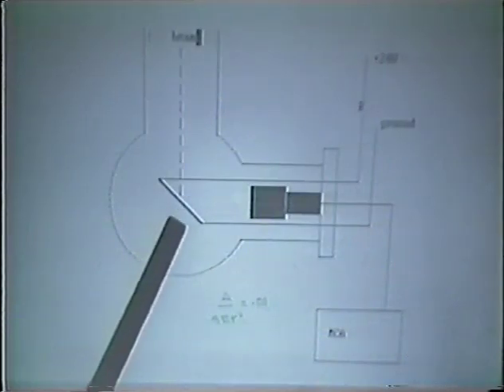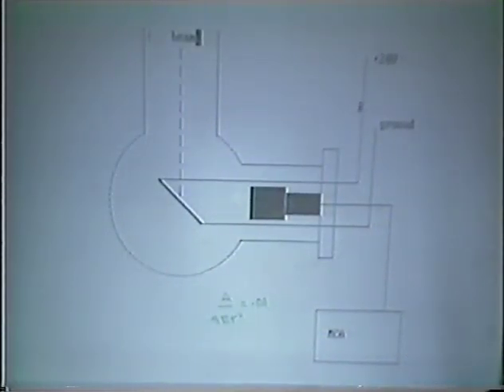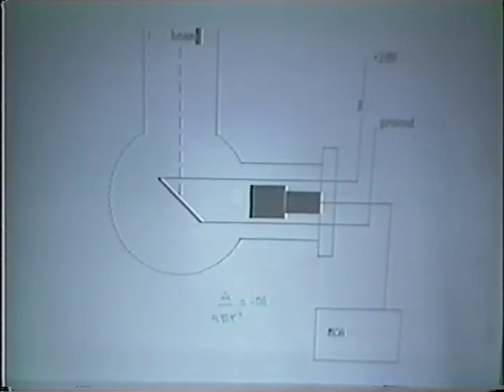And this is done very easily because you instantly are making a deuterium target just from the beam that stops in there, and then the subsequent deuterons that come in along the beam give you scads of protons and tritons from the DD reaction. Again, since the foil is thin, since the range of the deuterons is on the order of 1 micron, you can do excellent back angle spectrometry on these charged particles. They lose very little energy, if they have an energy of an MeV or so, going through 0.5 micron of metal.